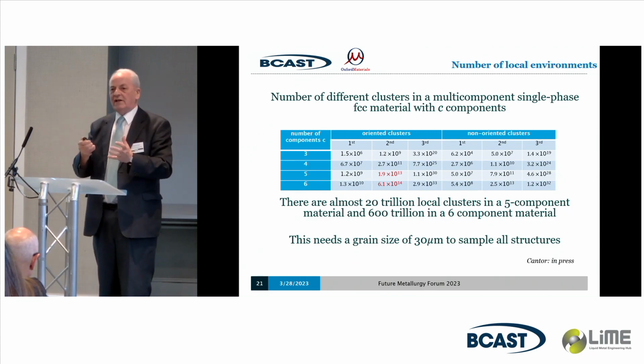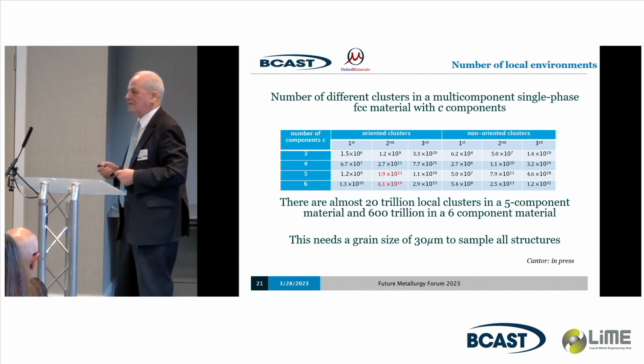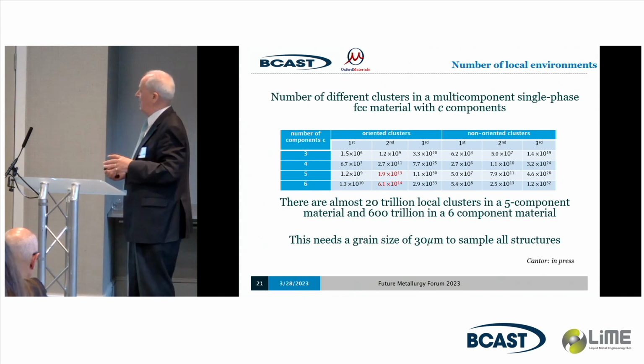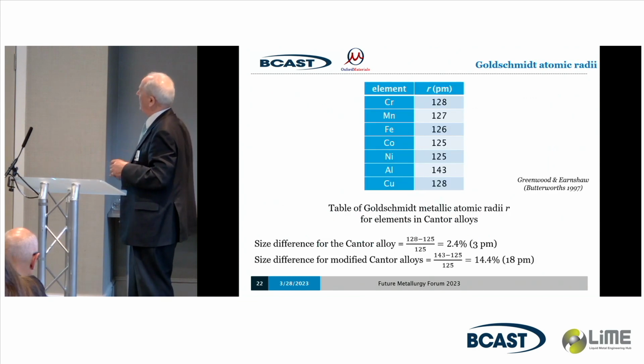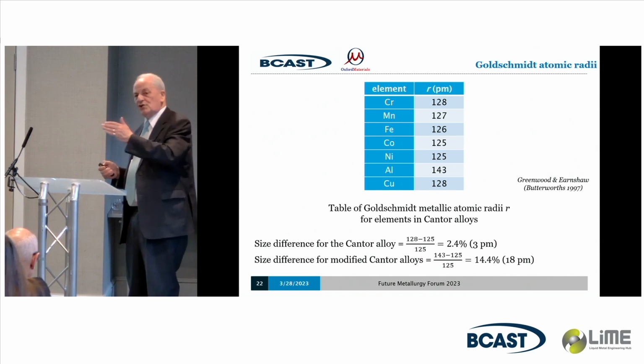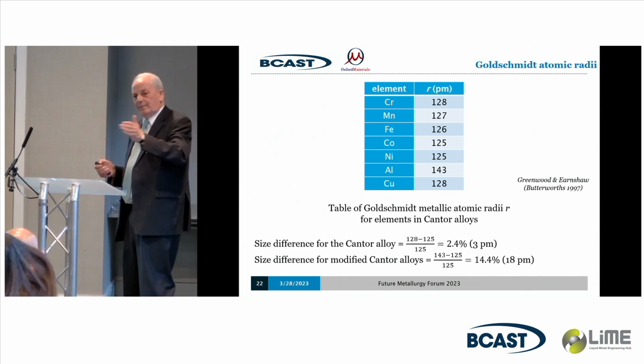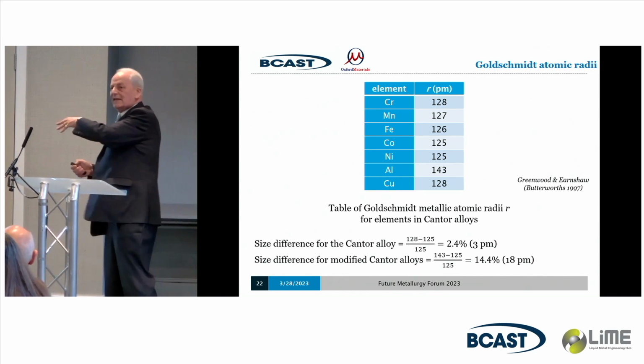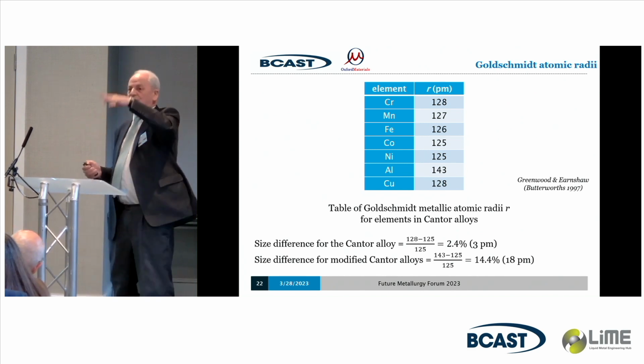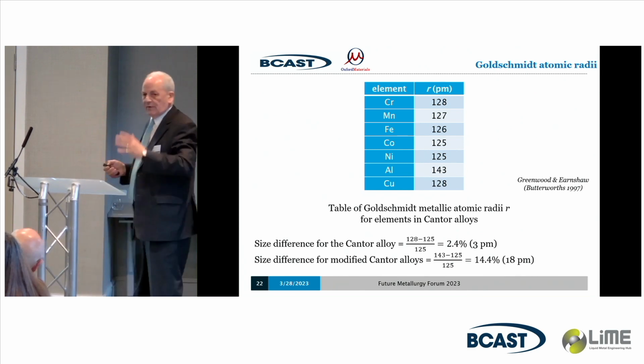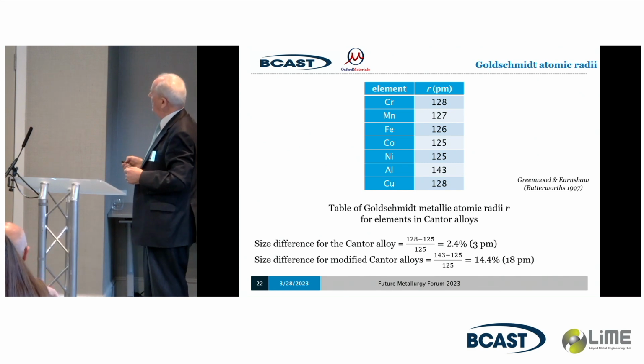It's like each grain is a big macromolecule in these materials. People have not made as much of this as they ought to have done, because I'm going to go on and show you. Well, first of all, let's see if it's right. By the way, I didn't point out, but because of that variation, you get local strains in the lattice, both mechanical and electronic. As you move around the lattice over 30 microns, the strain is going up and down, both mechanical and electronic.